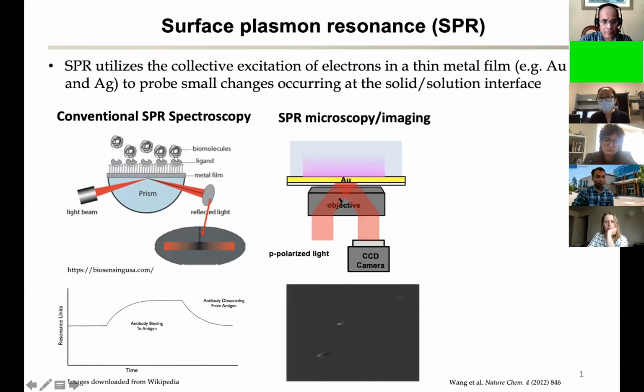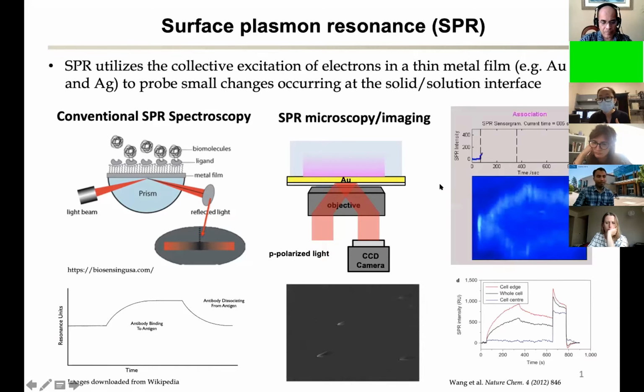Versus SPR microscopy or imaging, where we actually get imaging capability. We're still using the SPR signal, but with imaging capability. For example, you can monitor the binding process over a certain field of view, and you can see individual binding events simultaneously. Or if you're looking at a single cell, you can look at different portions of the cell, and by monitoring the changes at different positions, you can get different sensorgrams at different positions simultaneously. So that's what's good about adding the imaging capability to SPR measurement. This is one of the main techniques we use in our lab.